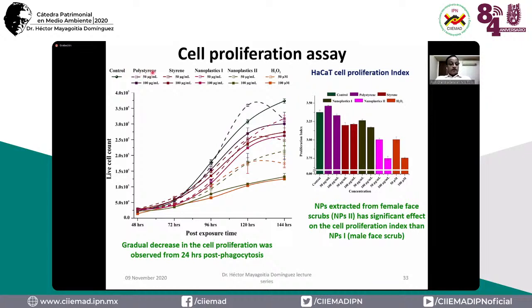We also did a cell proliferation assay. We did an experiment with control, polystyrene, styrene, nanoplastics 1, nanoplastics 2 of different size ranges, and also hydrogen peroxide. With a HaCaT cell line, a skin cell line, we saw a drastic fall in cell viability at different concentrations after the post-exposure time. The nanopolystyrene extracted from female face scrubs, nanopolystyrene 2, has a more significant effect on the cell proliferation index than nanopolystyrene 1 from male face scrub. A gradual decrease in cell proliferation was observed from 24 hours post-phagocytosis. So this was the finding.